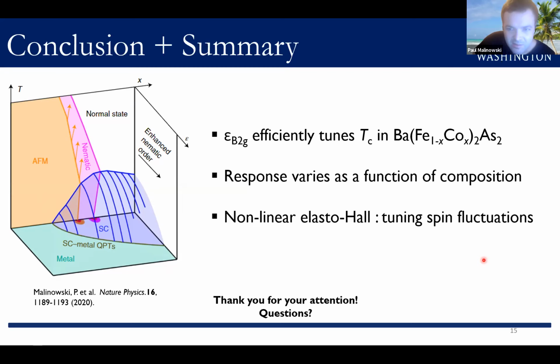Now I should say that there are many other possibilities here and caveats to that statement. So for example, we are not considering how the elasto-nematic coupling may be varying across the phase diagram, which I believe Matthias will be discussing in the talk directly after this. Additionally, anisotropic strain is expected to enhance the strength of stripe-type fluctuations, but perhaps it is isotropic spin fluctuations or other types that are actually important for the superconductivity. In any case, I think our work motivates a more careful study of the effect of strain on the nematic and spin fluctuation spectrum across the phase diagram and how that correlates with the effect of strain on TC. So with that, thank you for your attention, and I'm happy to take any questions.